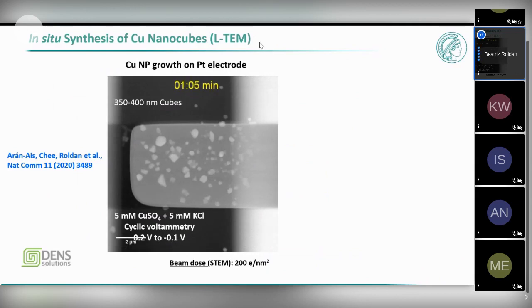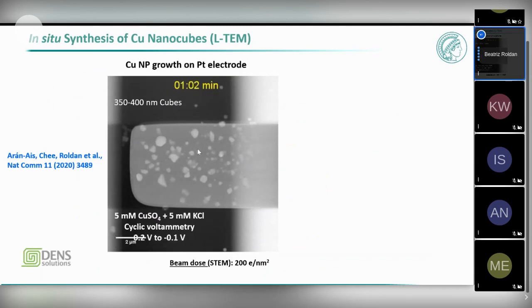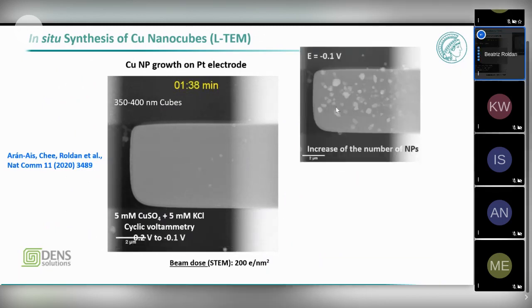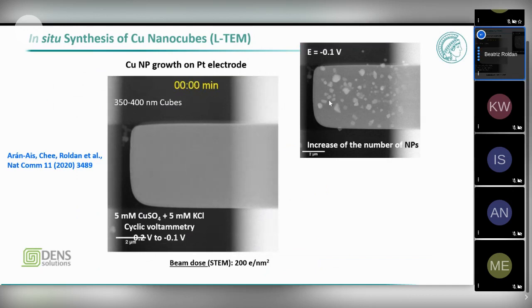We are inside a liquid cell in a transmission electron microscope. This is our electrode, and what you see changing in color here is copper nanoparticles. We have here a solution that contains copper. We have chlorine that is going to help us stabilize these 100 facets, and we are changing the potential, and you can see here that at some point we only get the cubic structures being stable. So this is how the synthesis looks for a certain potential.